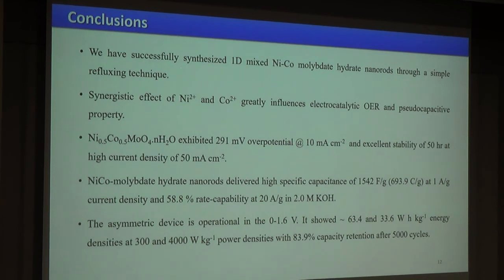So in summary, we have successfully synthesized one-dimensional nickel cobalt molybdate hydrate nanorod-like structures through a one-step refluxing method, and we also observed that the synergistic interaction of nickel and cobalt highly influences the morphology and electrocatalytic activity and also its energy storage activity. And this material showed low overpotential to achieve 10 milliampere per square centimeter current density in OER, and also good long-term stability at high current density.